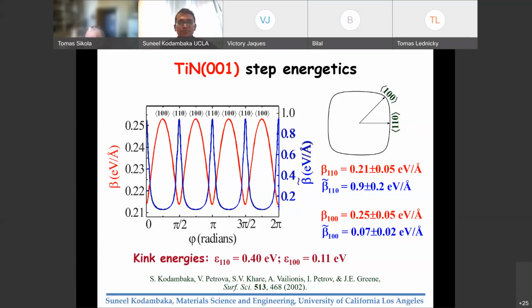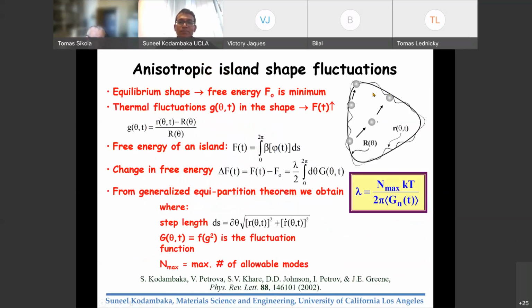You recall that I mentioned that you can also extract step formation energies from measuring the fluctuations in the shape of a given island. And so that we can do it. And the idea is very similar. So the equilibrium shape of the island has the lowest free energy. Any changes in the shape of the island, you increase the free energy. And a change in the free energy is a measure of the magnitude of fluctuations you observe. And this can be quantified.